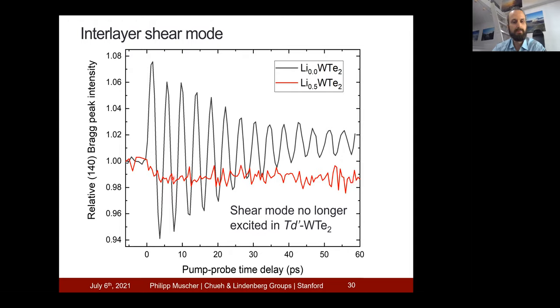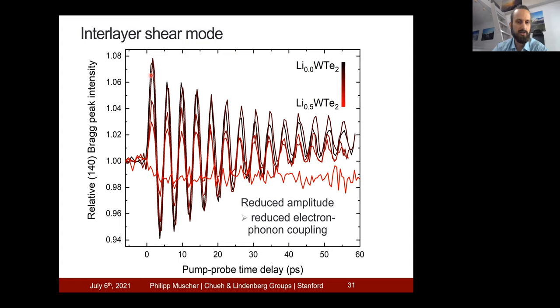Actually, we find that our laser pulse is no longer able to excite that type of shear mode in the fully lithiated sample. If we look at intermediate lithium concentrations, going from dark colors to brighter colors for more lithiation, we can see that the more lithium we insert, the more this vibration is reduced in amplitude. This indicates that there might be a reduction in the electron-phonon coupling, which is necessary for the laser pulse to be able to drive this vibration. So with this, I've shown you how we can, on an atomic time and length scale, look at a particular vibration and how it's changed by lithiation.